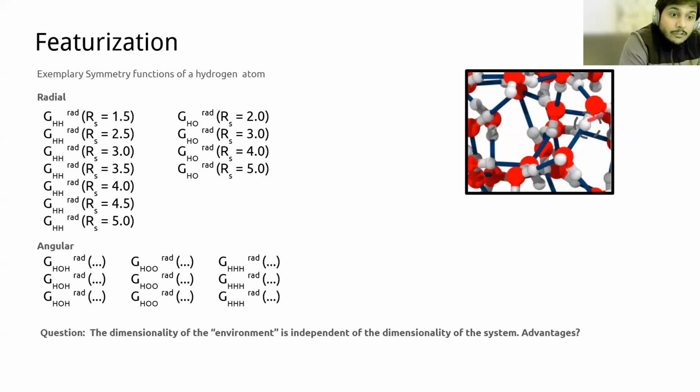So long story short, if you create a sphere of 6 angstrom radius and compute all the position vectors of all the atoms, you can recast that as a 17-dimensional vector, I think it was 17, where the first 8 or 9 of them would give you information on how atoms are arranged at particular distances around the central atom, and the rest would give you information on how triplets of atoms are arranged. And that becomes your representation, or your feature, on which you will learn.